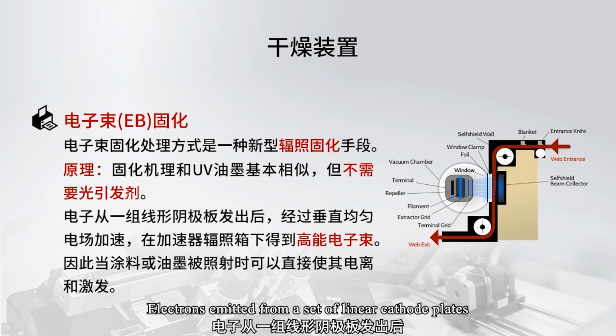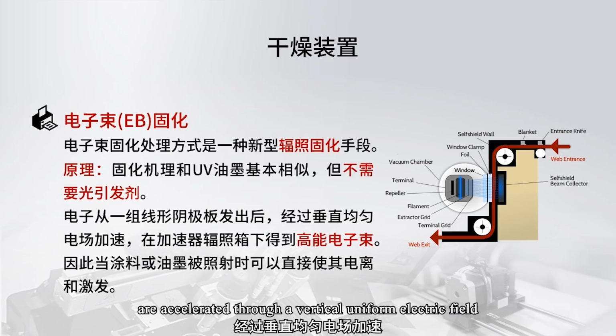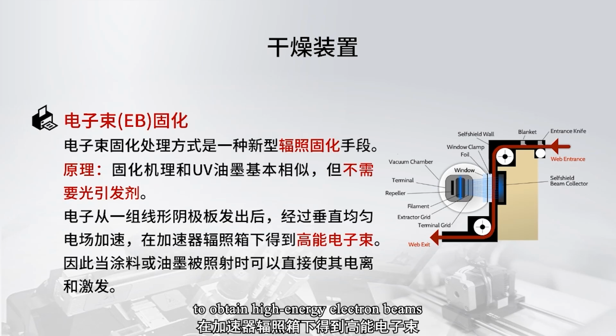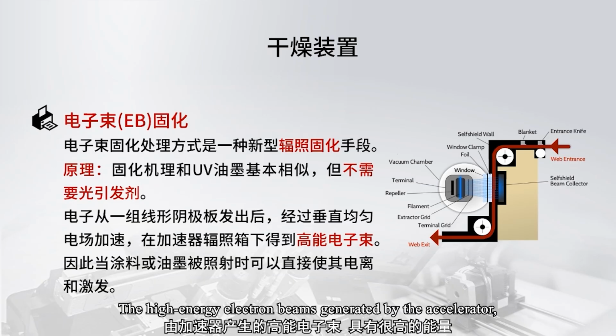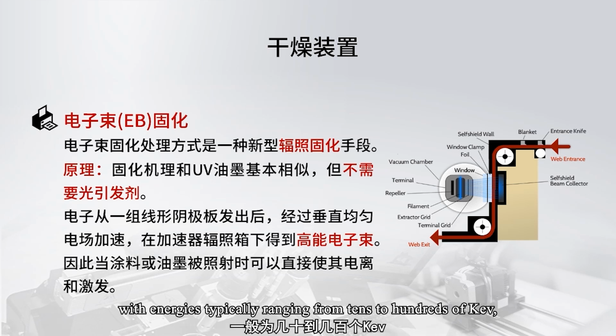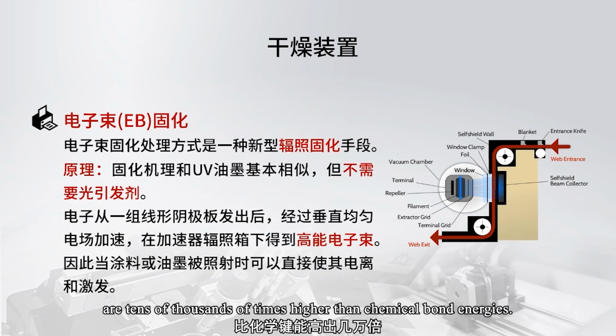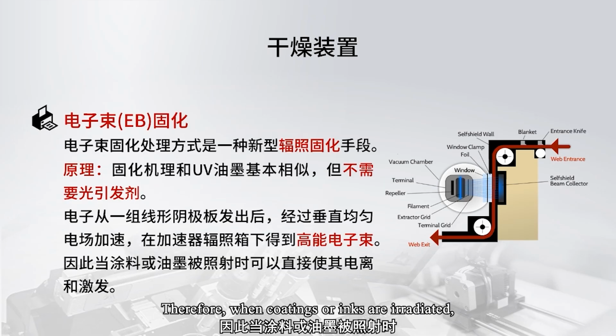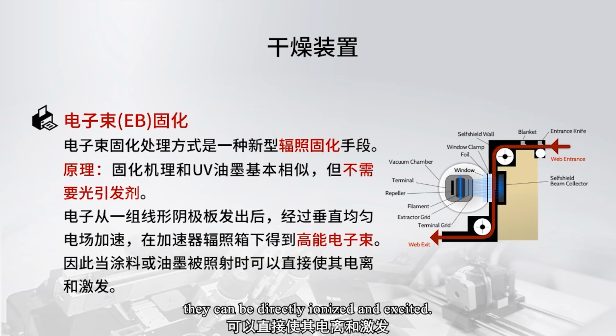Electrons emitted from a set of linear cathode plates are accelerated through a vertical uniform electric field to obtain high-energy electron beams under the accelerator irradiation chamber. The high-energy electron beams generated by the accelerator, with energies typically ranging from tens to hundreds of keV, are tens of thousands of times higher than chemical bond energies. Therefore, when coatings or inks are irradiated, they can be directly ionized and excited.